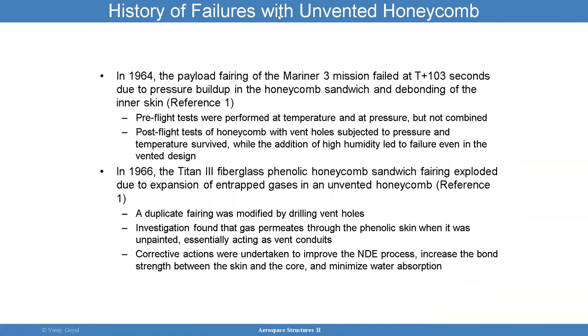There's more history of failures. In 1964, the Mariner 3 mission failed — post-flight testing of the honeycomb with vented holes subjected to pressure and temperature survived, while a high-humidity specimen led to failure even with the vented design. In 1966, the Titan III fiberglass phenolic honeycomb sandwich failed and exploded. Investigation found the pressure differential was causing the issues, and corrective actions were taken to improve the process and ensure good bond strength between the skin and the core.